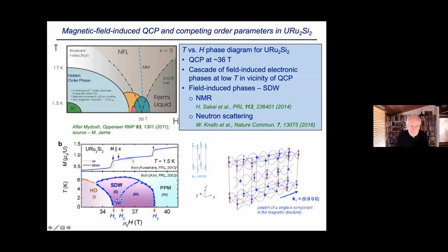But basically what I just showed you looks like this. And so there's superconductivity down here. This is a hidden order phase. And this is, I think, associated with the peak in the resistivity. So you have itinerant F electrons in this region, non-Fermi liquid in this region, Fermi liquid over here. This is a metamagnetic transition that occurs here. And then you get these different interesting phases. And one of these phases actually turns out to be associated with the formation of a spin density wave, which is shown schematically here, that's based on NMR and neutron scattering measurements. And I don't think all these other phase boundaries have been, I don't think this is understood in detail, but certainly there's a spin density wave in here. There's hidden order in this region right here. And then polarized paramagnetism in this region right here.